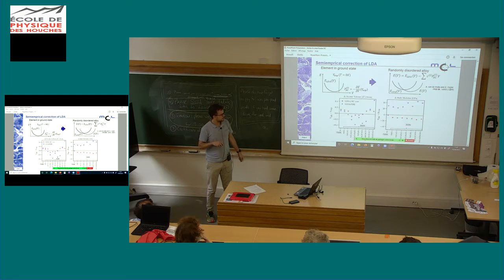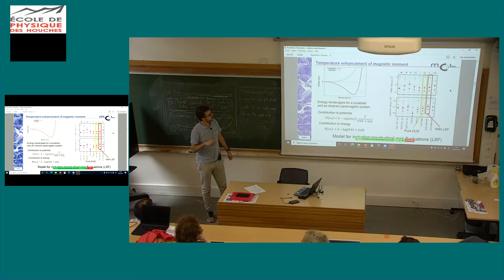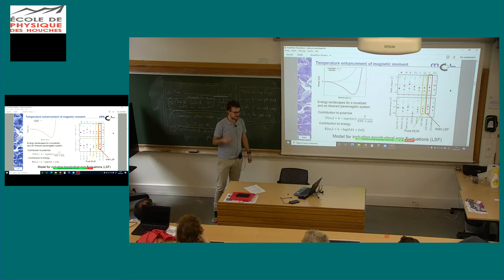And it really improves the prediction of the bulk modulus and also of the other linear elastic properties. So what do I actually mean? Just very short, with the temperature effect and of the magnetic moment. What you really see with these itinerant systems is that at elevated temperature, you basically get an enhancement of the magnetic moment.